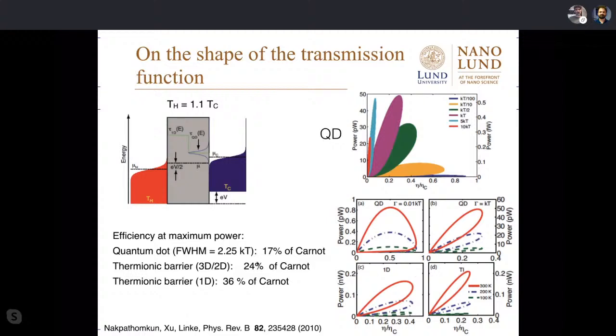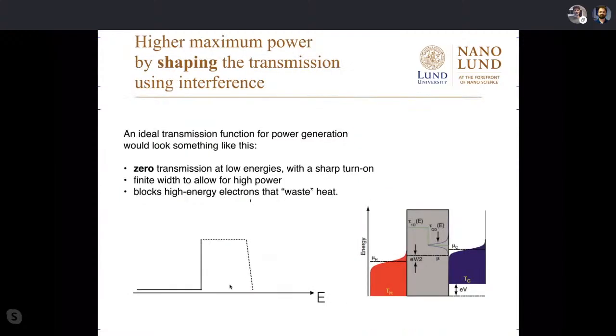So if you push this, you can find that at maximum power, a quantum dot, where you actually maximize power by opening up the resonance, only gives you 17% of Carnot, even in the ideal case, ignoring phonons. So this is lousy. Versus a thermionic barrier in 1D actually gives you more than twice of that. So this is what we use later.